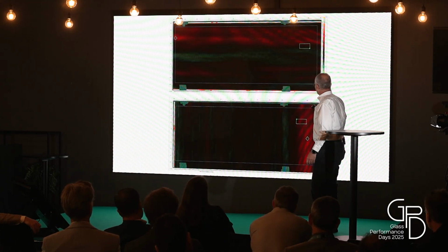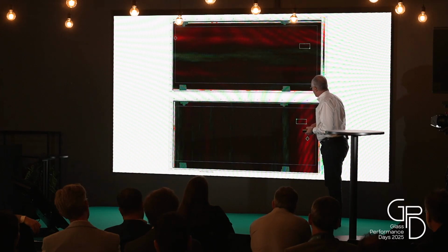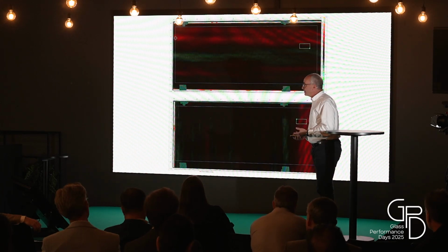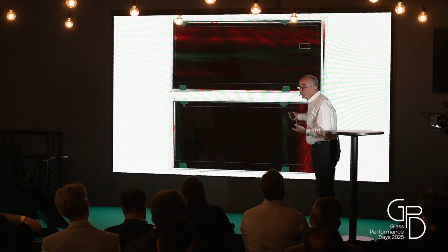But you see there's a concordance, and even in the numbers: even though it was a pretty good laminate, with this method we had 29 millidiopters of distortion. With the Inspector G software, we found 23. So it's pretty similar. There is a correlation between the visual zebra method, the automotive way, and analyzing the grid.